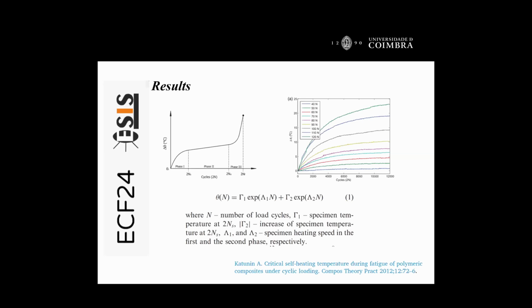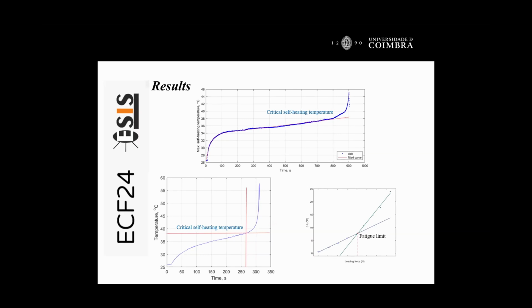By manipulating all these variables and using this equation, we can find the critical self-heating temperature here at this point. All this methodology is very well described in this paper, and in this curve we can see that for a fixed number of cycles, we can observe the effect of the load on the sample. Based on this theoretical approach, which is not new, we can obtain the curve here. This is a typical curve for a specific load. We can see here the curve that is composed of the three stages that were reported before.